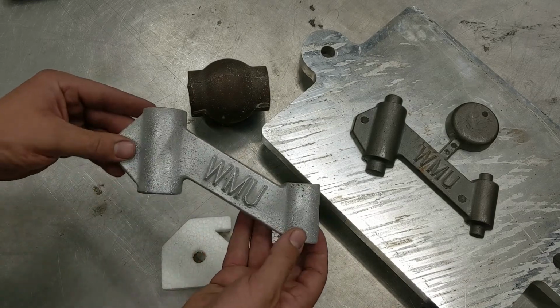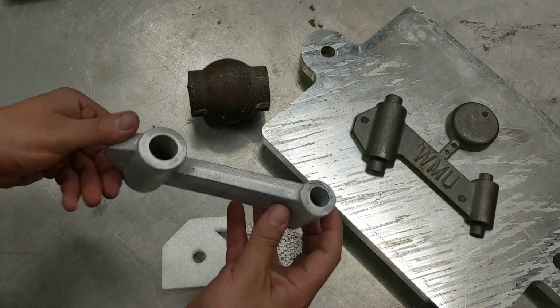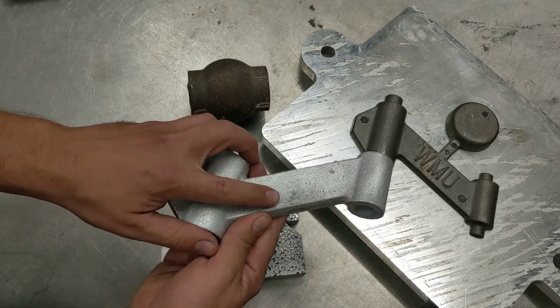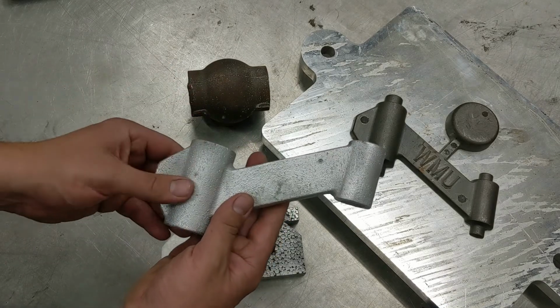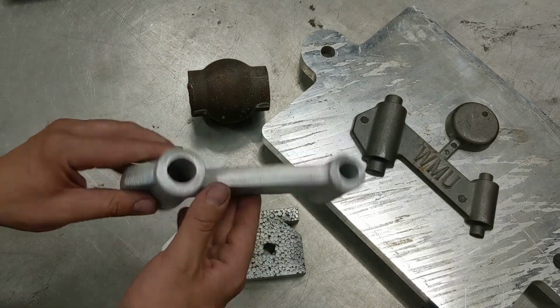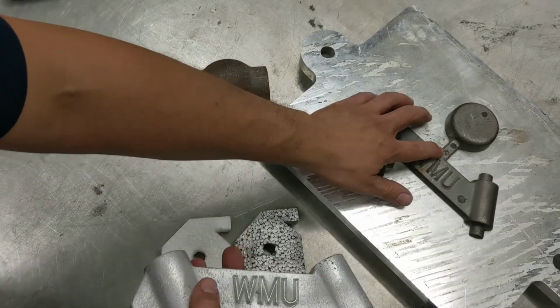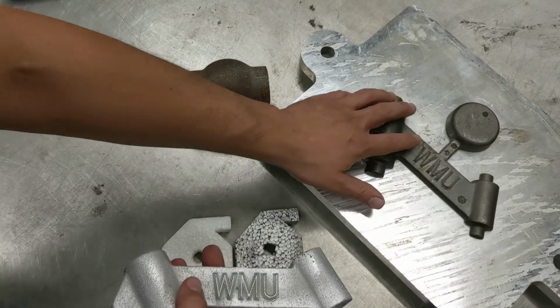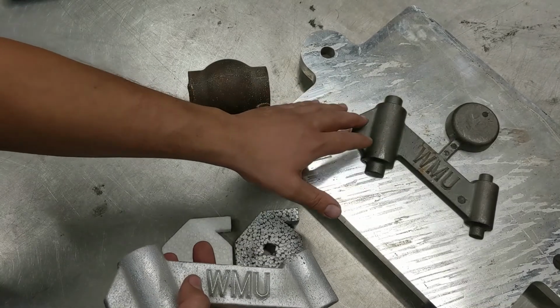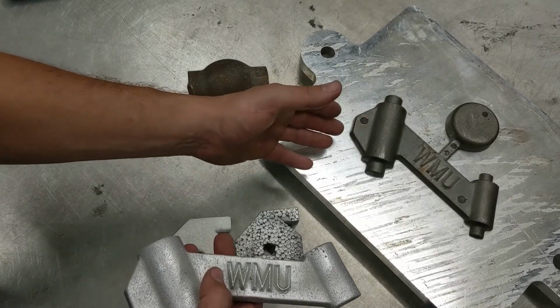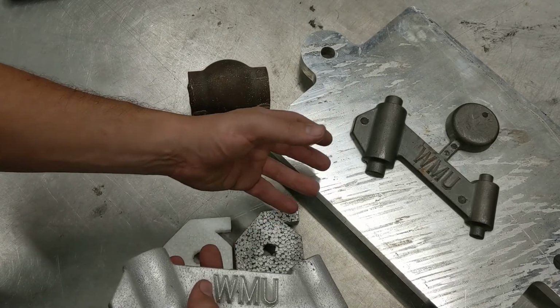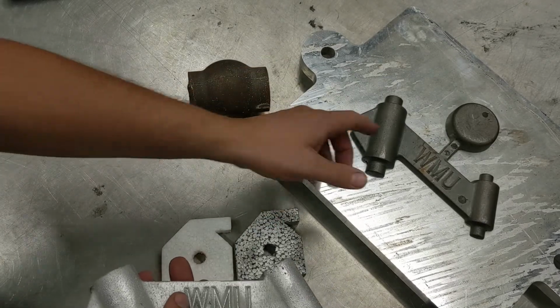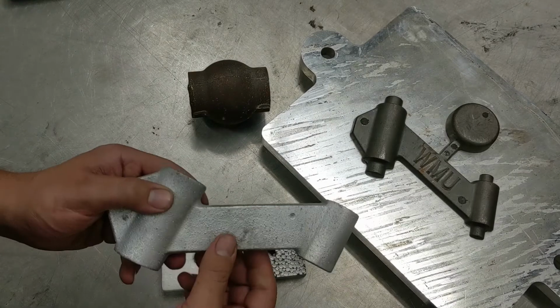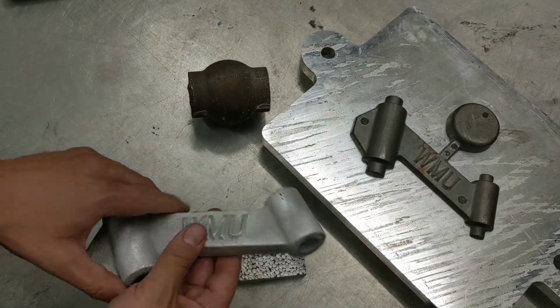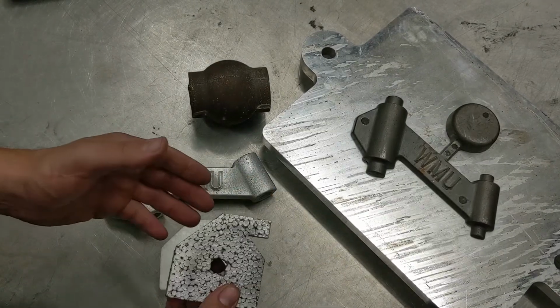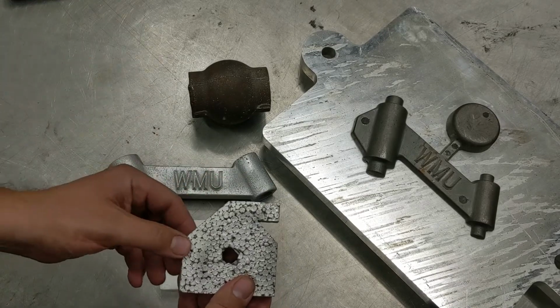The green sand casting itself also has some defects in it. There is a small shrink defect here. The result of that is that the gate, if you look on the pattern, how small the gate is, that froze off before the casting itself had completely solidified, which means that as the casting cooled, it couldn't draw in liquid metal from anywhere else, like in the pouring well or the riser. And so that created a defect in the part. We avoided that in the lost foam casting with that big heavy runner system.